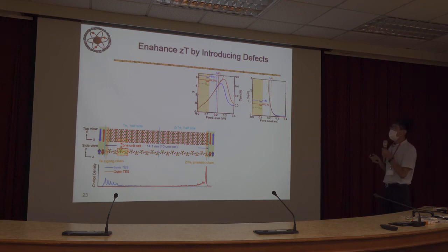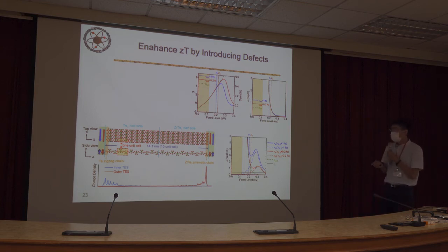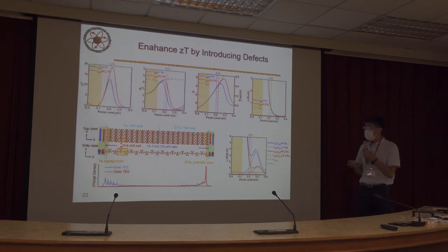Here we can see around the peak ZT energy, both the electrical conductivity and the Seebeck coefficient are dominated by their long-lived state part, while the electron thermal conductivity, as we mentioned previously, has a significant portion of the long-lived, short-lived inter-channel part. This term can be significantly reduced by decreasing the short-lived state relaxation time. So introducing defects in the middle regions can significantly reduce the electron thermal conductivity without noticeably deteriorating the electrical conductivity and the Seebeck coefficient, leading to the enhancement of RE and ZT.